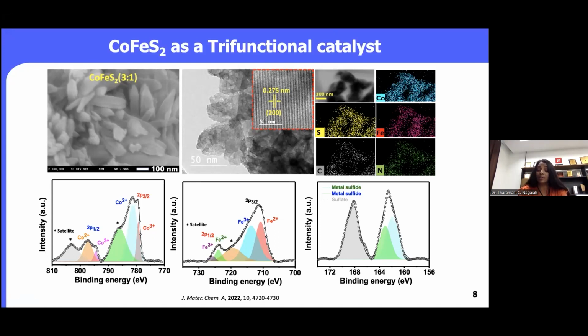The EDS elemental dot mapping further confirms the coexistence of cobalt, iron, sulfur, and also, more importantly, nitrogen doped carbon, which is intrinsic, since the material has been synthesized aiming to develop it, and which is responsible for the oxygen reduction reaction. The presence of both cobalt and iron, and also the oxidation states of these metals, has been confirmed by XPS analysis. The lower binding energy is due to the metal sulfide, and the higher binding energy is due to the presence of sulfate.